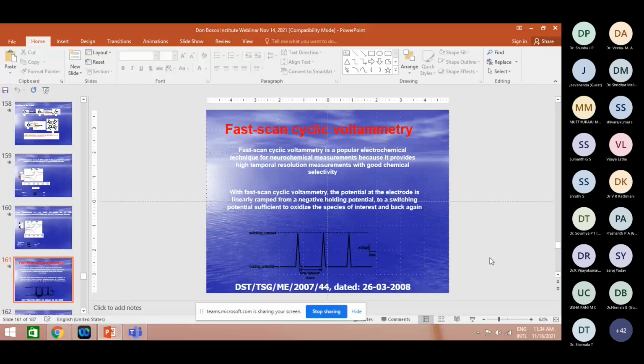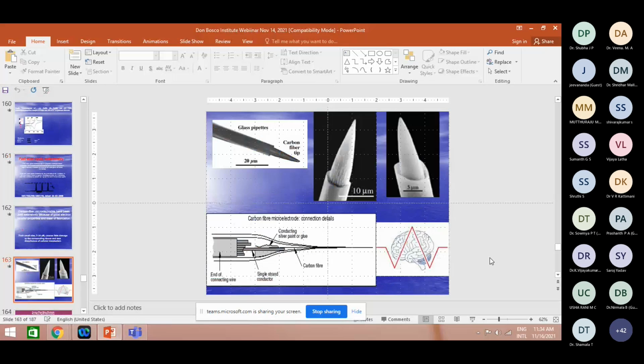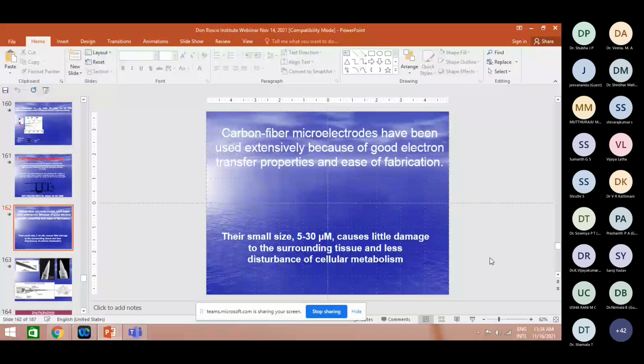You need to use carbon fiber microelectrodes. Carbon fiber microelectrodes are very important, and they have very good electron transfer properties and ease of fabrication. Normally we write ease of fabrication. When I started this research at the University of Virginia, I got really upset because getting these electrodes to work is very difficult. If you prepare 100 carbon fiber electrodes, only 10 will work. If you prepare 200, maybe 15 to 20 will work. Because if you take one long hair and cut it longitudinally 20 times, you will get only one hair.